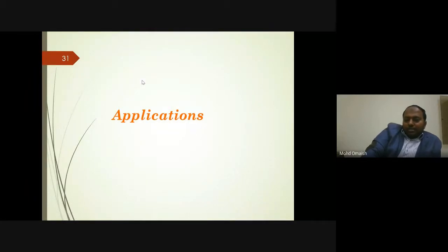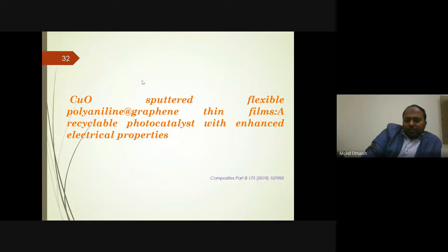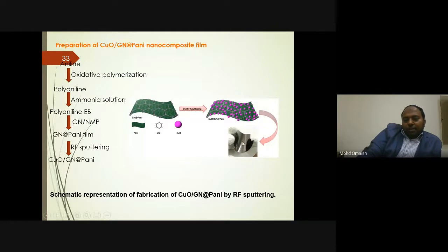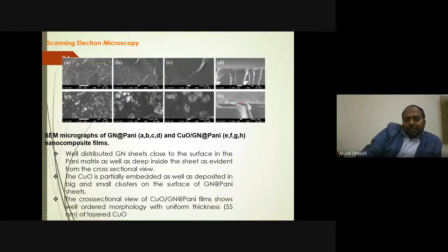And coming on to the applications of polyaniline, this is one of our previous papers. From this paper, I can tell you that we prepared a conductive, flexible polyaniline film, which was sputtered with copper oxide by RF sputtering, and we got a very good flexible RF sputtered polyaniline graphene copper oxide composite film. Here we can see the sputtered copper oxide in contrast to the polyaniline graphene film, in clusters or as single particles. They are well distributed, and we can see a very thin, 55 nanometer film of this copper oxide.